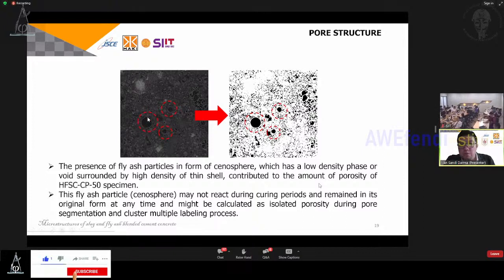You will have the cenosphere, which contributes to the porosity. And then this fly ash particle may not react during the curing period and remain in its original form at any time, and might be calculated as isolated porosity during the pore segmentation and cluster multiple labeling process.